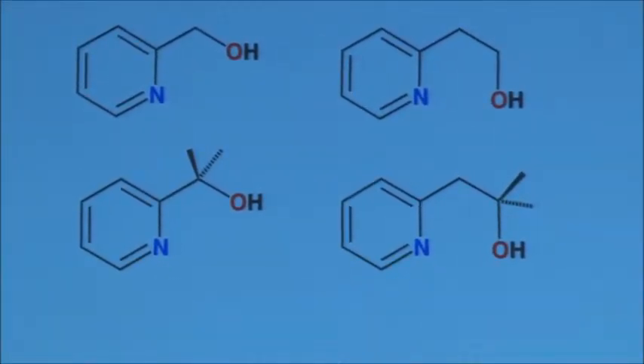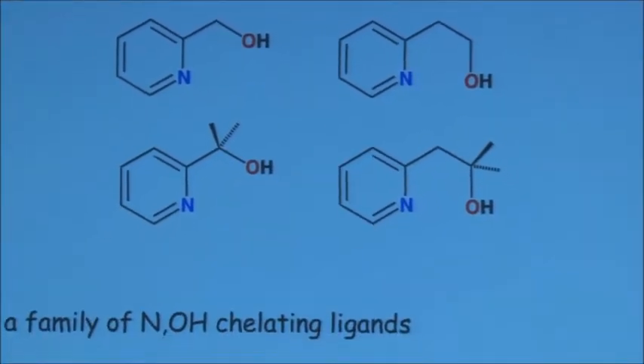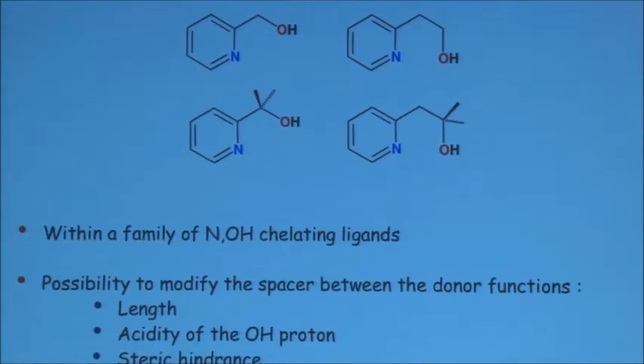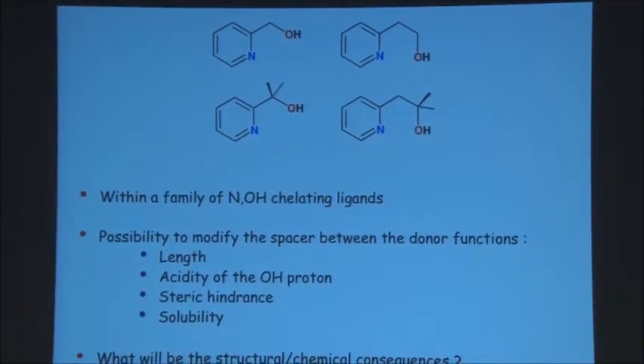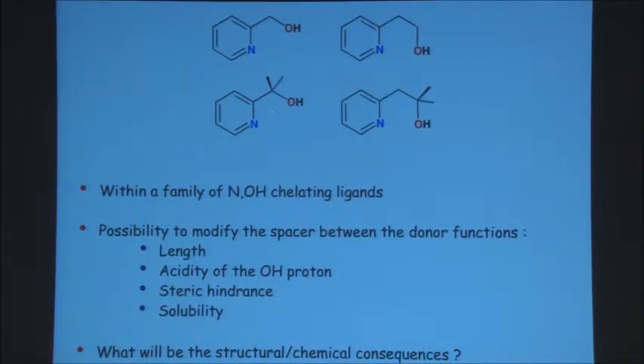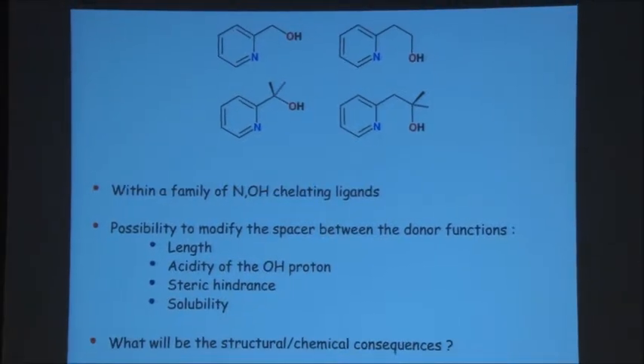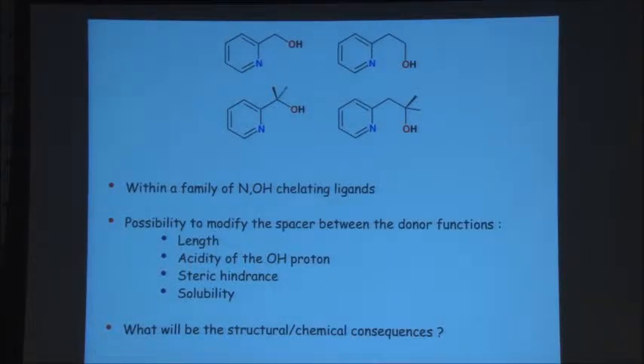That will have an impact on the acidity of the proton because of the increased electron donicity through the methyl groups, for the C1 spacer or for the C2 spacer. So with this family of ligands, which look very simple, you can already investigate stepwise a number of parameters. You can vary the length of the spacer. You can vary the acidity of the proton because of the electronic effect. Then the steric hindrance: the 2 methyl groups on 1 carbon do have a steric effect, so they tend to open the angle, the so-called gem effect that was very well known in organic chemistry decades ago. And of course, the solubility may also be influenced by the substituents.